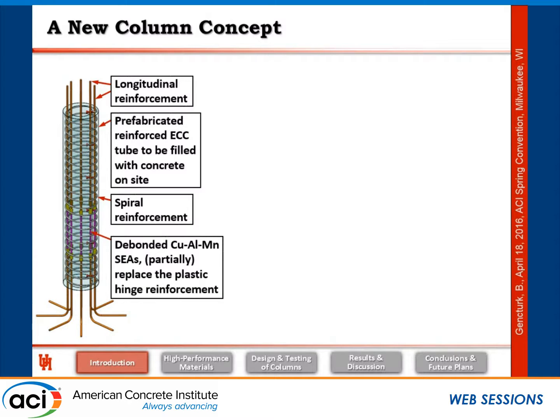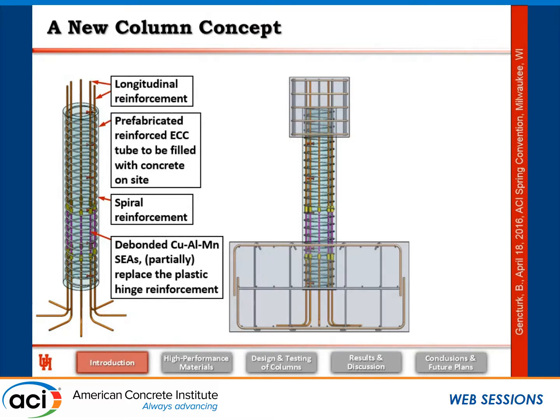Then there are these debonded SMAs. I'll call them SEAs rather than SMAs in this presentation because they're in superelastic mode, and they're a different type. They are not nickel-titanium alloys, but they are copper-based alloys. The reason why we're using copper-based alloys, although nickel-titanium is more robust, is because nickel-titanium alloys are very expensive. So I really wanted to ask Mustafa after his presentation how much he paid for those number 10 diameter nickel-titanium bars, but I don't want to hear the answer. Probably it's in the tens of thousands. The reason we wanted to use the copper-based is because they're significantly cheaper than the nickel-titanium alloys, but obviously they are still in the development stage and they are not as robust. So there's a lot of variability in the properties of these copper SEAs.